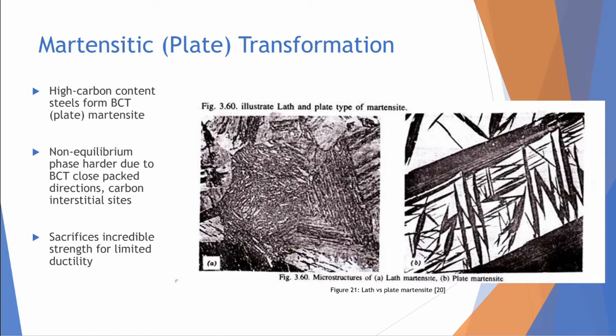The quenching medium used is vegetable oil due to its property of extracting heat much slower than water, preventing excess stress formations which can lead to cracking. However, the hardening from using oil is less than of water due to the slower cooling rate. From this information, the graph tells us that slightly greater than 50% of the material's composition is made up of martensite. Specifically, plate martensite forms during quenching due to the steel's high carbon composition of 0.6%.